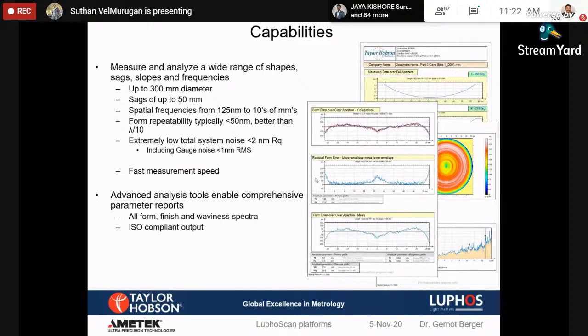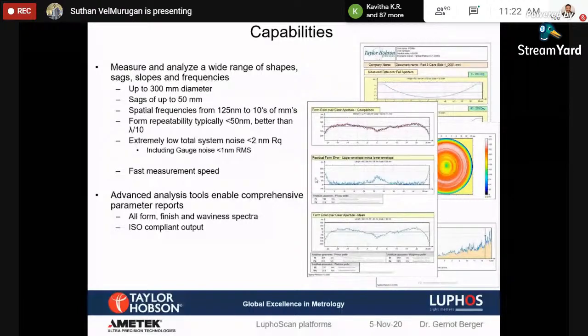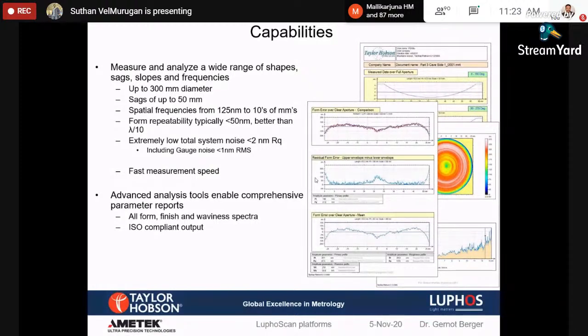And the repeatability, or the accuracy, we can say is less than 50 nanometers. And the very important parameter of any machine: what is the inherent error, or what is the noise of the system, basically. It is very well defined. It is less than 2 nanometers, the inherent error of the measuring equipment. For example, I'm looking for a 50 nanometer form error of the component from the manufacturing machine. So my measuring equipment should be at the lowest level of error. I cannot eat away 50% of the tolerance of the component produced from the manufacturing machine. So if my component is produced at the level of 50 nanometer accuracy, my error is just 2 nanometers, which is negligible.